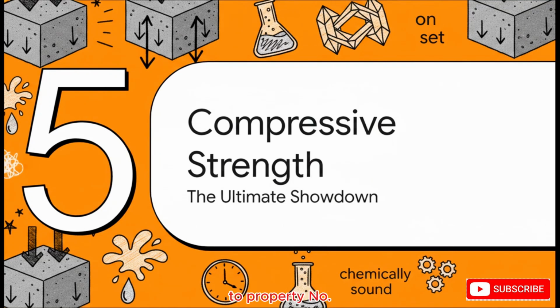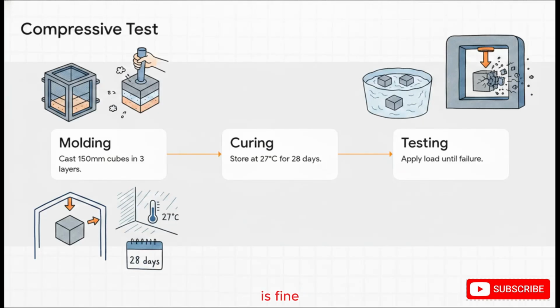Moving on to property number 5, compressive strength. So, the cement is fine, the water is perfectly proportioned, it sets right on time, and it's chemically sound. Now, it is time for the ultimate physical showdown. How do we know how much weight our concrete can actually hold up? Well, first we take these 150 millimeter steel cube molds. We fill them with concrete in 3 distinct layers, and we tamp each layer exactly 25 times to force out any trapped air voids.